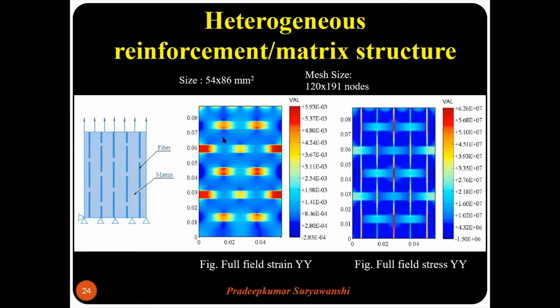So typically in this case, suppose we assume that a crack initiates in this place, it propagates horizontally like this, and it will stop as soon as it reaches the inclusion, here there is an inclusion or reinforcement. It will move parallel to the inclusion, and it will move to another possible area where cracks may initiate. Like this, all the cracks initiated at different places in the bulk material will propagate and they will meet, and that will result in final complete failure of this composite structure.